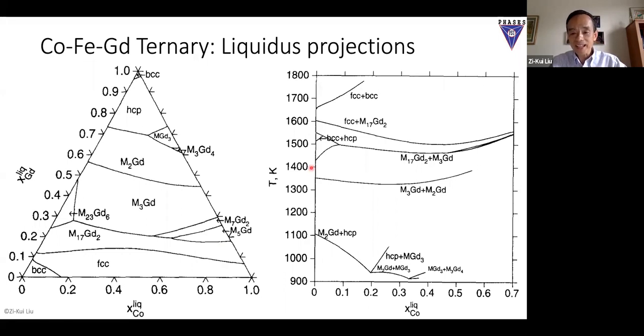Now I can see the exact temperature here. For example, this is a eutectic temperature, there's another eutectic temperature, and you have a maximum here. So this gives you different information—you get the invariant transformations, you get the temperatures—so you combine the two together, you can figure out what is temperature and composition from this diagram. So this one, see both of them.